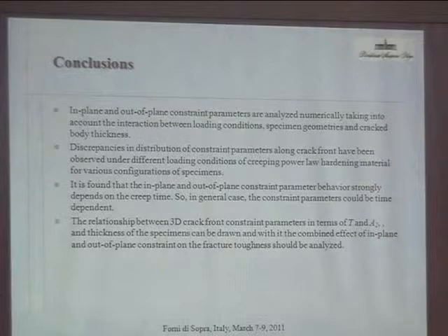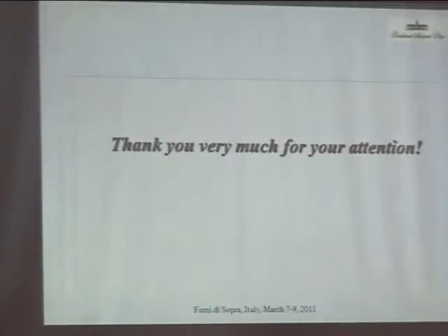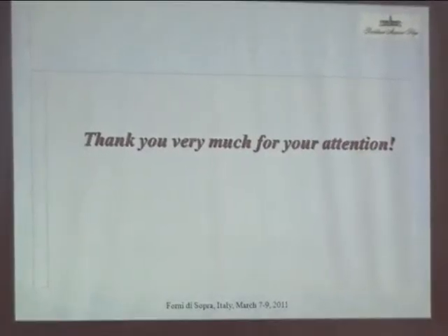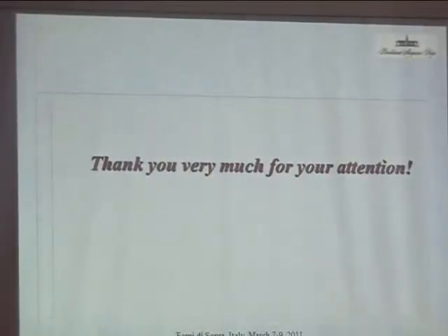And conclusions. In-plane and out-of-plane constraint parameters are analyzed numerically, taking into account the interaction between loading conditions, specimen geometries, and crack body thickness. We have considered distribution of constraint parameters along the crack front under different loading conditions of creeping hardening material for various specimen configurations. It's found that in-plane and out-of-plane constraint parameter behavior strongly depends on the creep time. So in the general case, the constraint parameter would be time-dependent.